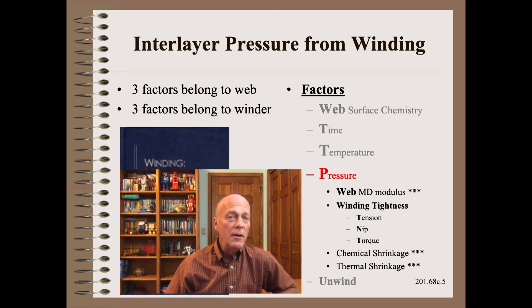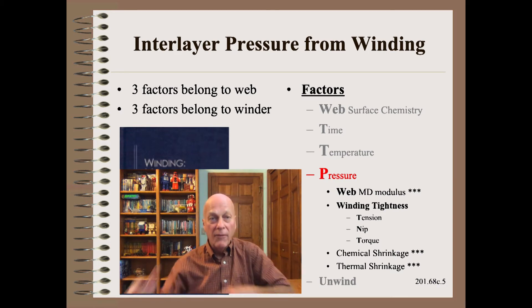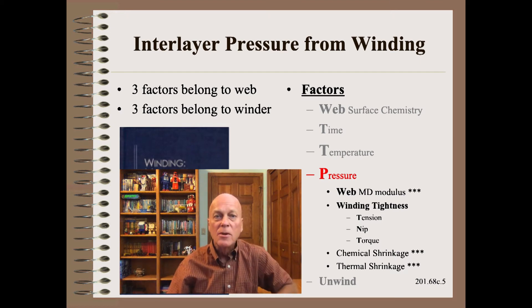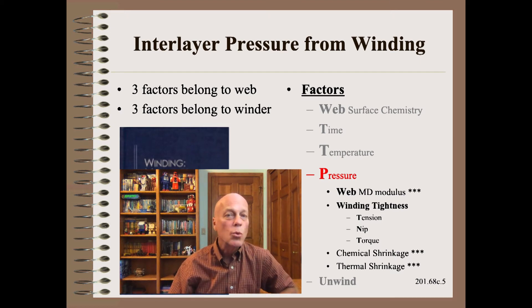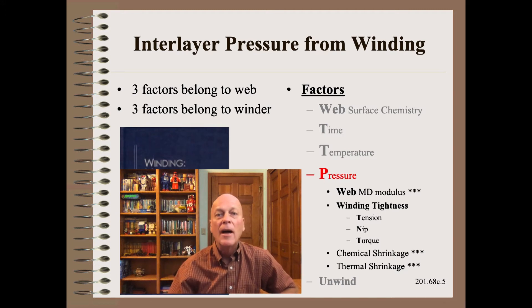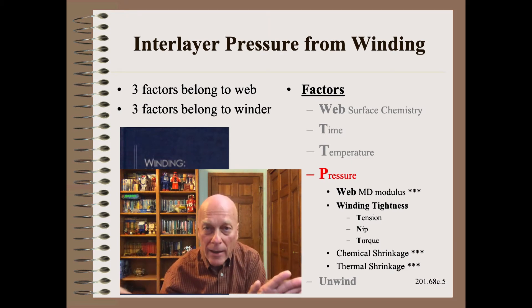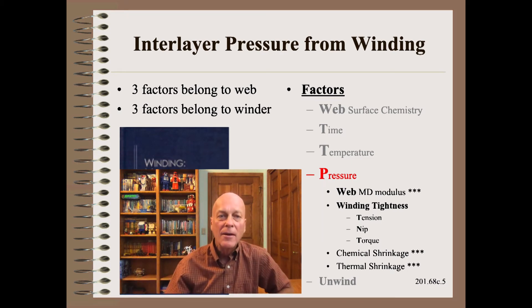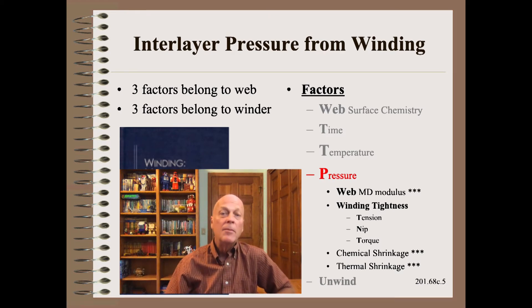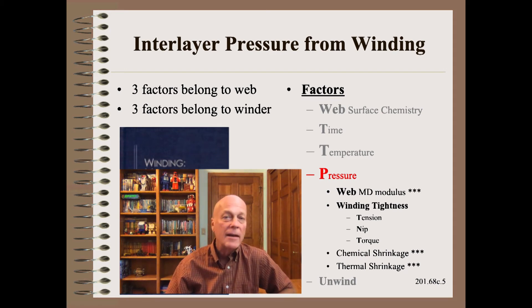If you look at the list of factors that affect pressure, you will see that as many as three belong to the web and as many as three belong to the winder. Thus, the expectation that you can kill blocking by winder tension taper or winder curves, for example, might be wishful thinking or even perhaps quite naive depending on the detail.